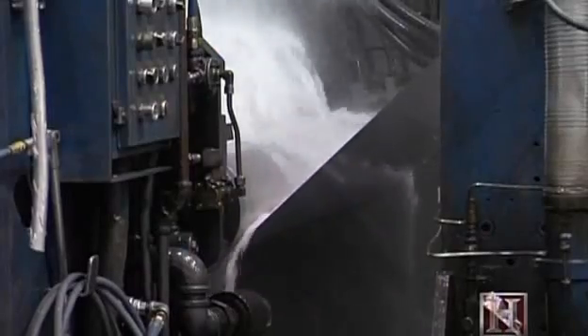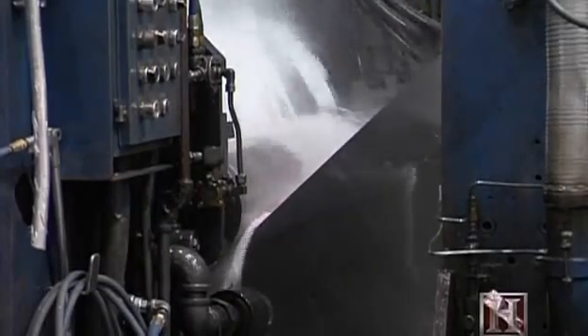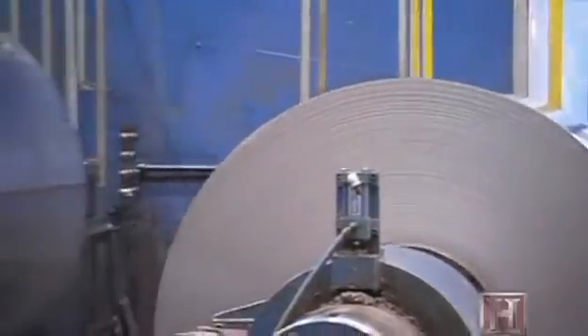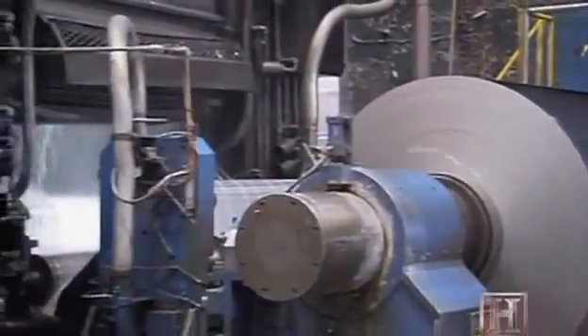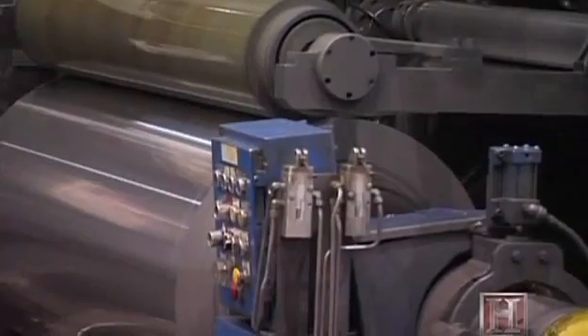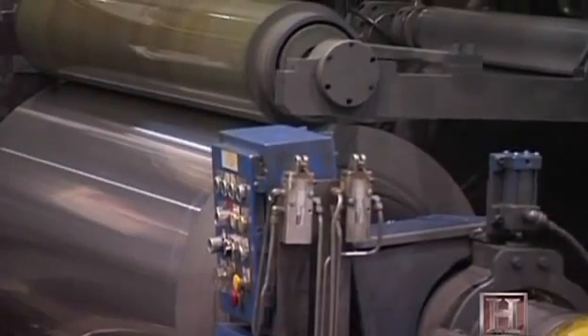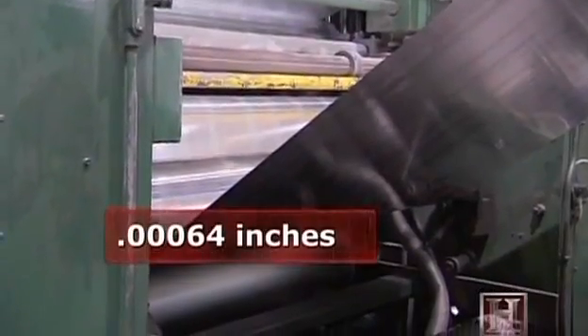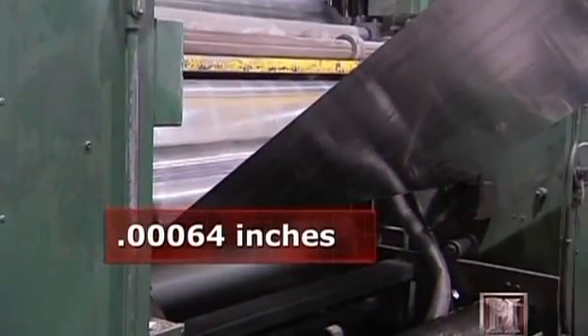Since the outer sides of each sheet contact the highly polished, lubricated roller surface, they emerge shiny. And since the inner sides touch only each other, they emerge with a matte finish. After the doubled foil exits, each single layer is only 6.4 ten-thousandths of an inch thick, 6 times thinner than a sheet of standard copier paper.